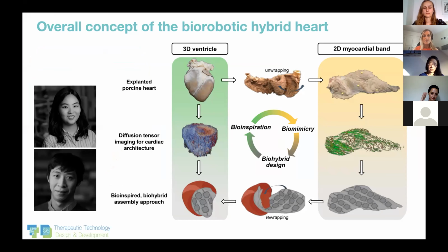The idea of this was that we took an explanted porcine heart, so a pig heart. Pigs have a similar size and structure to human hearts, so it's good for testing cardiac devices. And we used a technique that has been reported before in the literature for unraveling the left ventricle, or the entire ventricles of the heart. So something called a helical ventricular myocardial band. And actually what you can do is essentially unwrap the whole heart into one band. It's really fascinating. So then we could take a part that corresponded to the left ventricle, which is the pumping chamber that pumps the blood around the body.